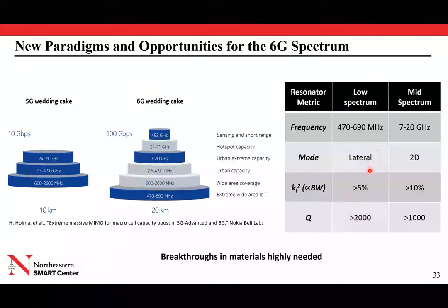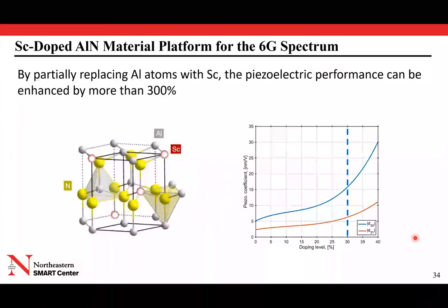Now, if we look at the requirements of these new bands that we discussed, the low spectrum and the mid spectrum 6G, you see that for the low spectrum, we really need Kt squared larger than 5% and a Q larger than 2000. And in this case, you cannot really use a thickness mode, right? Because to go that low in frequency, we'll have to use very thick piezoelectric layers that is not sustainable from a manufacturing standpoint. And when you scale at high frequency, you would want to use maybe a two-dimensional mode of vibration, but you need a Kt squared larger than 10% and a Q larger than 1,000. So there is really nothing available that has this performance. And that really required breakthroughs in material properties.